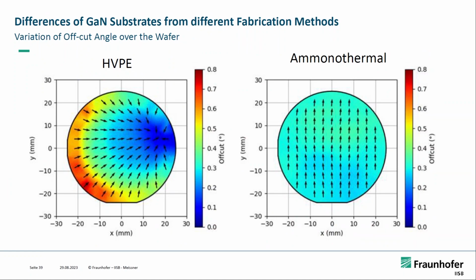What are the differences in terms of off-cut? If you compare the ammonothermal and HVPE, you can see here is a mapping. This is the off-cut angle, which can go from 0 to 0.8, so it can be also quite large at the edges, for example. And you also see that it's odd-shaped, so it's not symmetrical, it's like a wave or an uneven shape, whereas the ammonothermal crystals are much better in this sense.